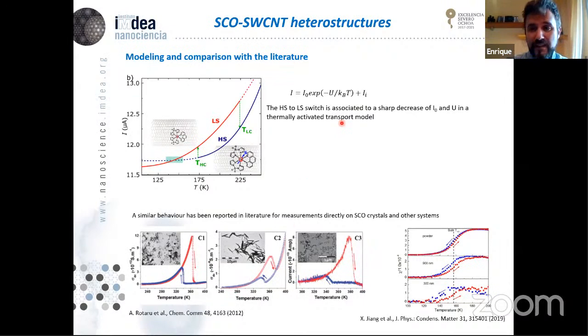I have to highlight that in this case, the hysteresis is there intrinsically to the molecule, so they can see it in the magnetism of the molecules. This is not our case. So in our case, the hysteresis is opening. But we had this very recent report in 2019 that showed that by creating very thin films of these spin crossover molecules, where you don't have a hysteresis when it's large enough, by making the thickness of the film smaller, down to 300 nanometers, you start to open some hysteresis cycles. So I think this is precisely what is happening in our carbon nanotube, with the difference that in our case it is much more confined. Okay.